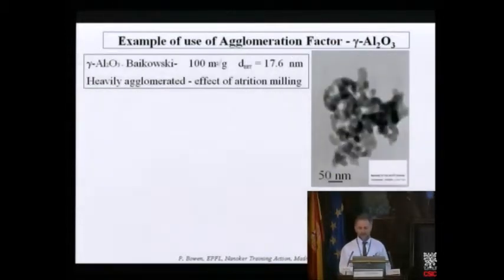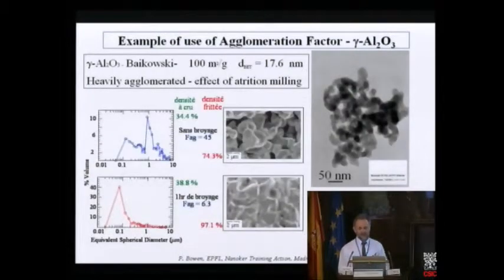We look at the Baikowski example. So this is what it looks like in the TEM. We see our nice primary particles. If we take the as-received powder, we slip cast it, we get 34% green density. We try and sinter it, we get a maximum of 74% density. This is at 1600 degrees centigrade, where, as you saw this morning in the first presentation, with standard alumina powder you expect 99% density. You have this problem of aggregation.